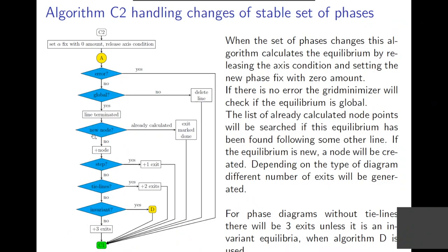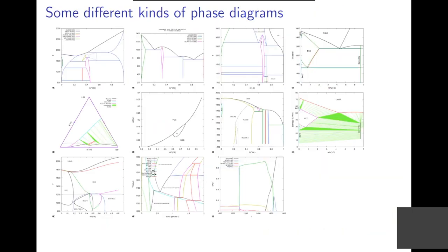So you first check if you already have found this node from another way, as I said for the sigma phase in the iron chromium nickel. If the node already exists, you mark an exit in this node point as done and finish. If it is a new node, you create the node. And if it's a step calculation, you just follow a line, you create just one more exit in the same line. If you have tie lines in the plane, that means a normal binary diagram or ternary isoplet, then all node points have two exits. Because, as I showed in this diagram, a node point here always has three lines meeting. And so when you come to this point, you have two exits.